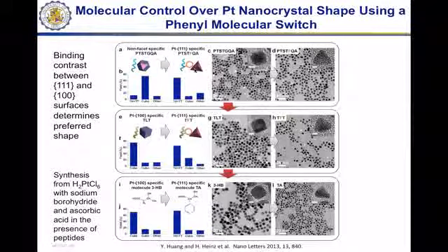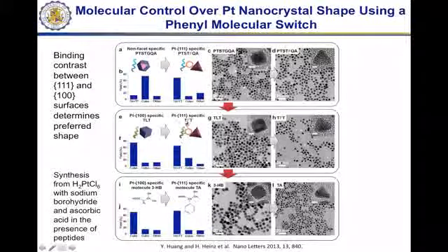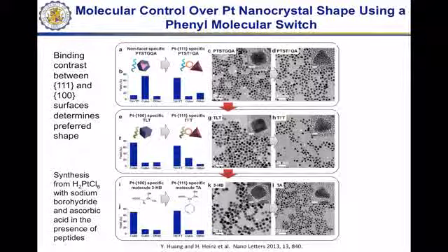And then experimentally by our collaborators at UCLA, the group of Yu Huang, it was shown that you can change the nanocrystal shape if you use those selectively designed ligands. So instead of, say, cube octahedra, you can make tetrahedra, or instead of cubes, you can make tetrahedra, just by a single mutation in that peptide sequence. The same works also for non-biological molecules. If you add a phenyl ring in here, then you have a strong driver to support the formation of 111 facets.